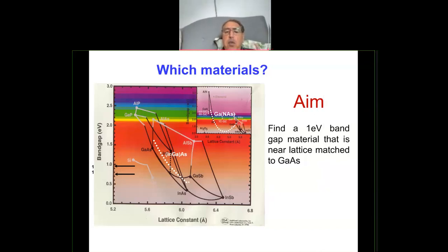So for example, if we take gallium nitride and here gallium arsenide. So when we add nitrogen to gallium arsenide, we would have expected, like these energies here, that the band gap should go this way, from gallium arsenide to aluminum to gallium nitride. Should just increase, like here, for example, gallium arsenide, aluminum arsenide, the energy should increase as you increase the aluminum content, go from 0 aluminum to 100%. People were expecting the same thing when you go from gallium arsenide to gallium nitride. If you add nitrogen, 0 nitrogen to 100% nitrogen, so the band gap should do this.